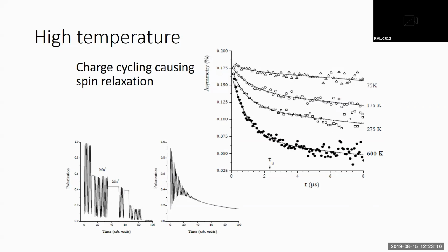What's happening on a microscopic timescale for a particular muon? Say it starts, the muonium is oscillating between 1 and 0 approximately polarization. At some point it ionizes, locks in that polarization, and it catches another electron to form muonium again, oscillates again, starting from this value back down to maybe 0, and then loses the electron again, and so on. So a series of bursts of oscillation. If we just take all the averages for all the possible different ionization times, you get a damped oscillation, plus a rapid, followed by slower polarization.